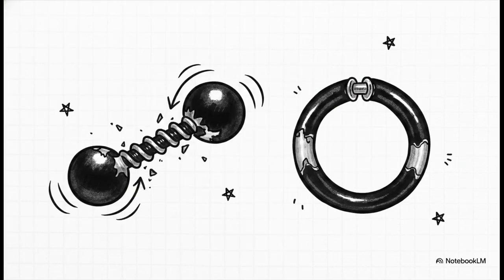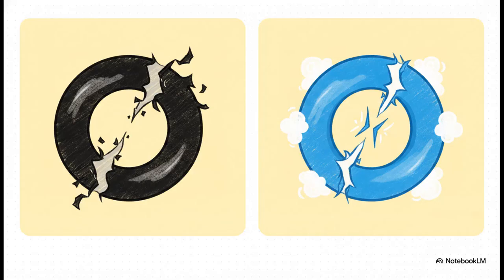So here is the reality of how PVD fails. Because PVD is a separate adhering layer on top of the titanium, it is super vulnerable to friction. Think about it. If you have threaded components screwing together or a client constantly fidgeting with a ring closure, that friction will eventually grind the coating completely away. Those high contact points are always going to be the first to wear down and permanently expose that silver gray substrate underneath. Now compare this directly to anodized titanium.